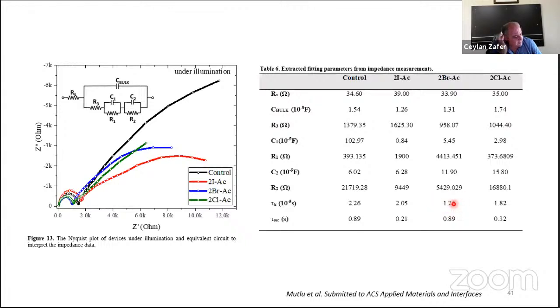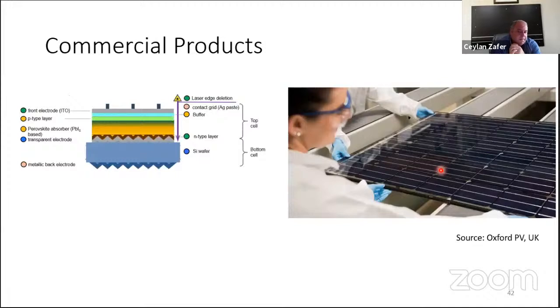This means faster transport within the structure, and the recombination time is longer. This means a slow recombination takes place within the perovskite structure. This comes with the recombination resistance of the material with the benzyl bromide compared to the others. It's a very huge recombination resistance. And that's why